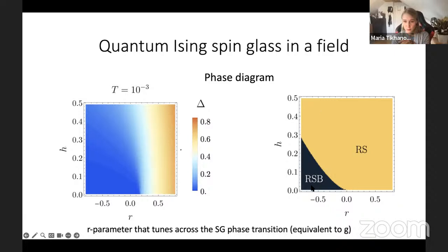So measuring the order parameter, what happens? Actually, I think this is based on free energies. Whichever free energy dominates, that's the one that gives you the corresponding phase. So H again is the longitudinal field, and R is something related to the transverse field. And you have the RSB phase and you have the RS phase, which is the replica symmetric phase. This is the replica symmetry breaking phase.